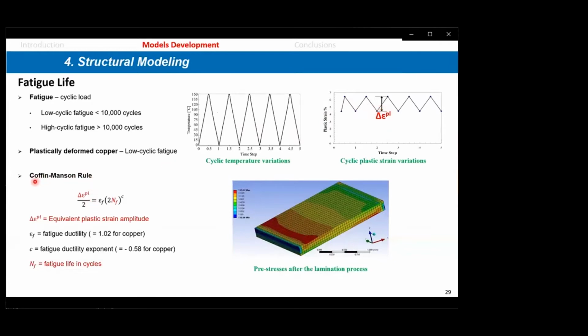It is because we are using a fatigue model to predict failure called the Coffin-Manson model, which gives the number of cycles to failure as a function of the amplitude of plastic deformation that the copper ribbon suffers. This model involves two parameters, which are the fatigue ductility and the fatigue ductility exponent, and these are taken from the literature, measured. So N is the fatigue life in cycles, and this is what we are looking for, and this will give us the number of days that the panel will be functional before it fails.